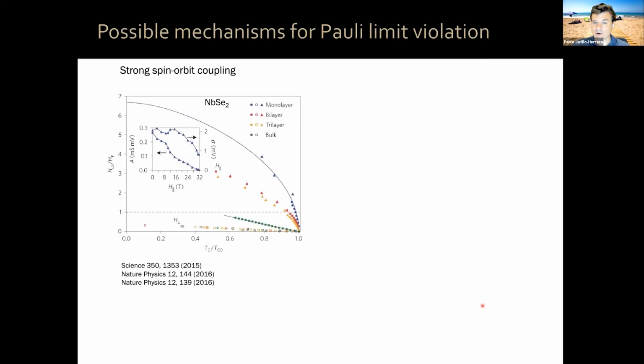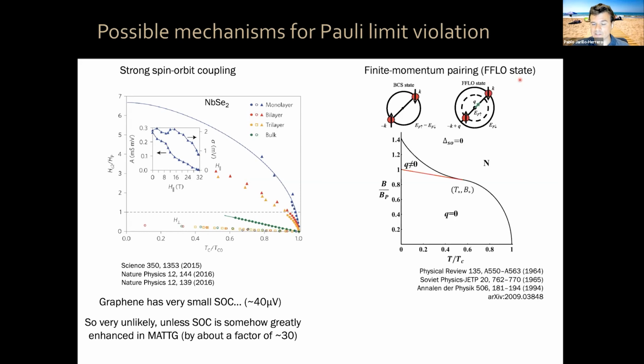The possible mechanisms for Pauli limit violation, let me just mention this: strong spin-orbit coupling, FFLO type of physics. None of these apply to magic angle twisted trilayer graphene because graphene doesn't have spin-orbit coupling, and because FFLO states occur only at very low temperatures, and lead only to a small increment in the Pauli limit. We see a 300% increase, not just a few percent.